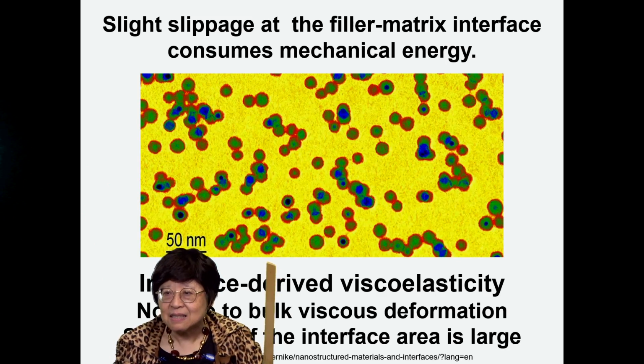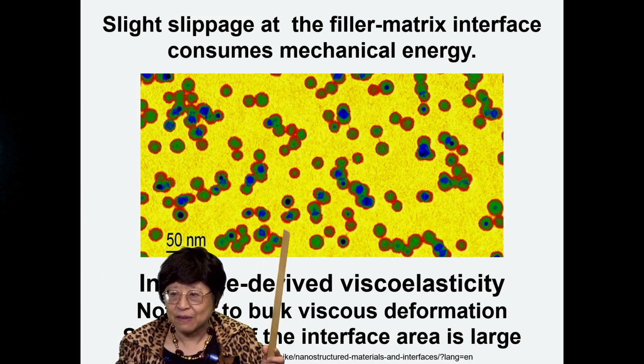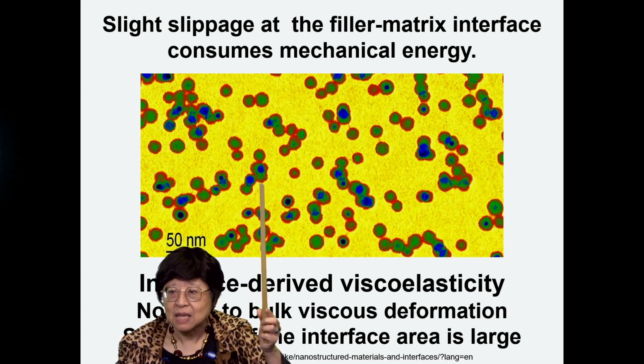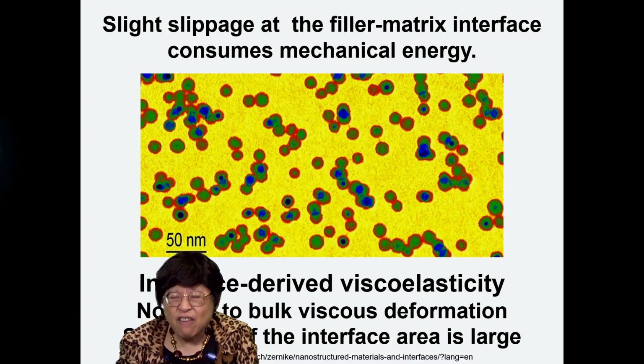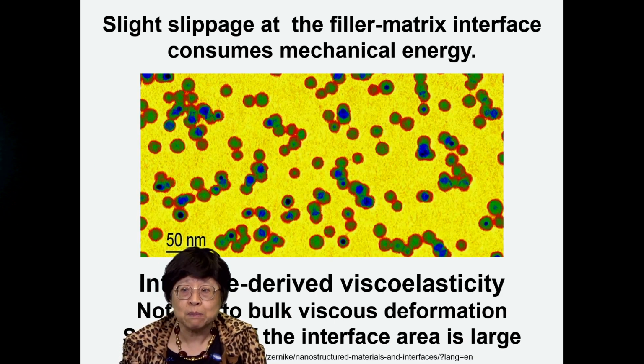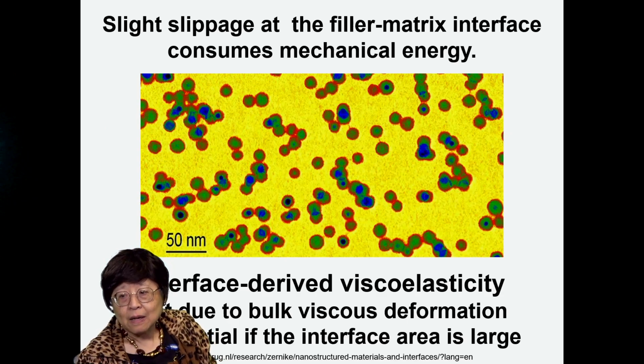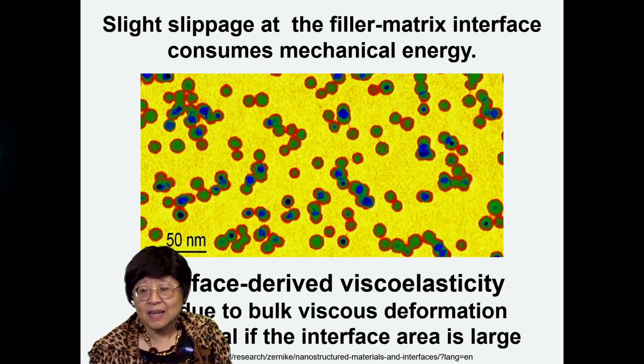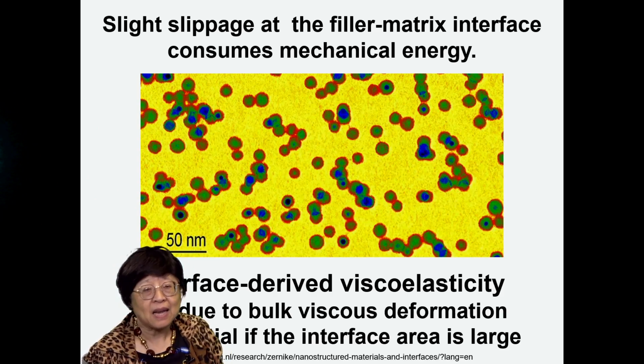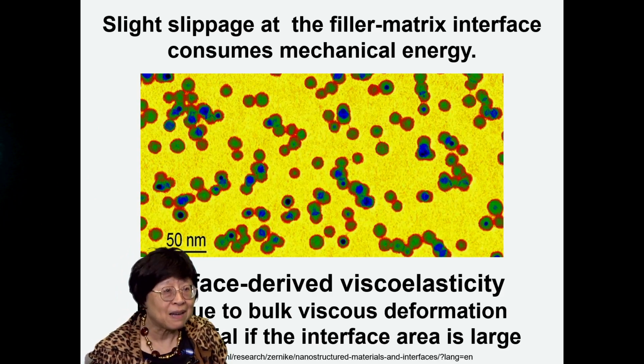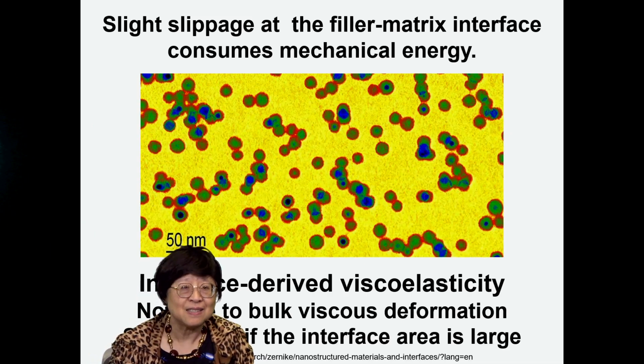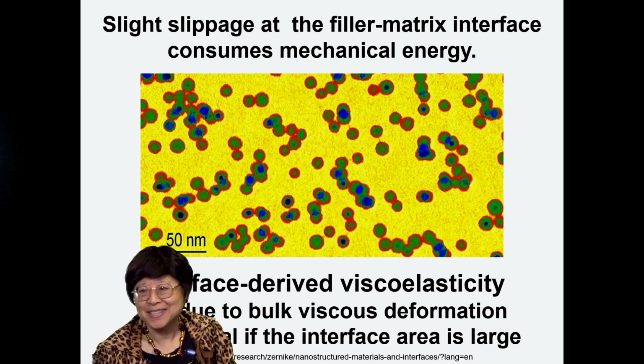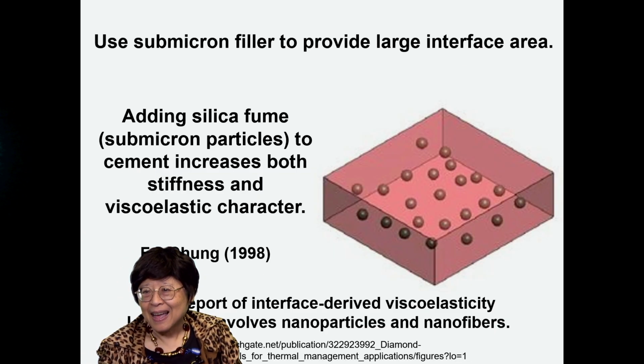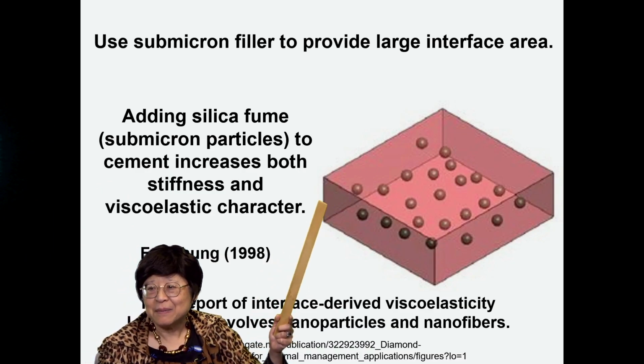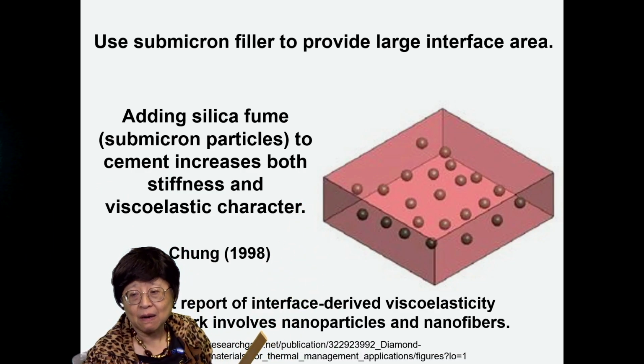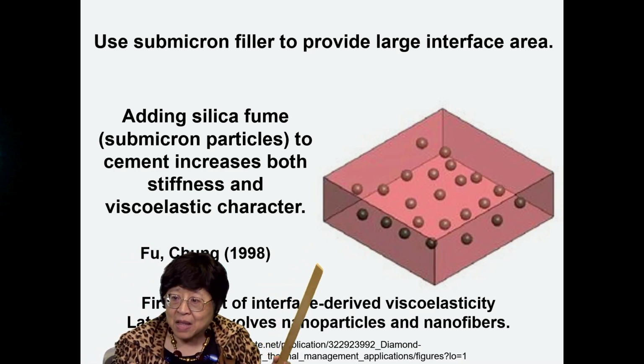And I realized that slight slippage at the filler matrix interface, such as this particle reinforcement and the matrix in yellow, that very slight slippage at that interface consumes mechanical energy. And if you have a large interface area, then it can amount to quite a bit of mechanical energy dissipation. This new mechanism is called interface-derived viscoelasticity. I just coined that name myself. And back in 1998, we provided the first report of interface-derived viscoelasticity.